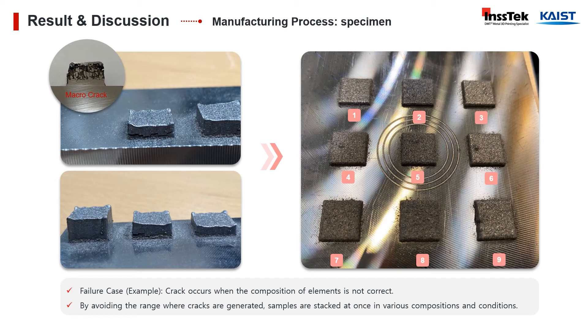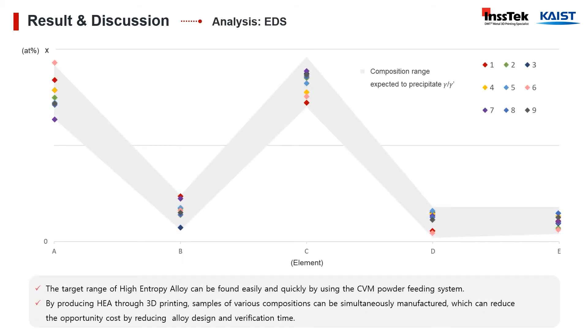In general, when developing a new alloy, the composition design is carried out by predicting the section where defects will occur in advance. However, the actual specimen might present cracks, contrary to our projections. In this study, the composition range that causes cracks was confirmed in a short period of time through actual testing. The optimal composition range was quickly and easily configured, and finally, nine specimens could be stacked at once. As a result, in the energy dispersion X-ray spectrometer analysis, we could observe that all nine samples satisfied the target range, and from the nine targeted specimens, we could obtain promising results from one of them.